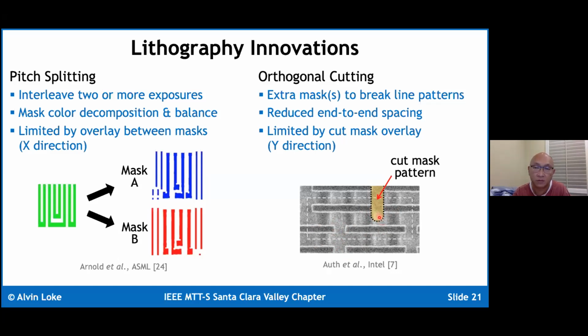Okay, so this technique is used quite extensively. In fact, it's used so extensively that quite often the cut masks are also pitch split because the pitch of the cuts themselves is so tight. But once again, with this particular technique, just like pitch splitting, lithography overlay is a limitation. If, for instance, you imagine this cut pattern being misaligned in the Y direction, you can clearly see it's going to pinch off this pattern here at the bottom.